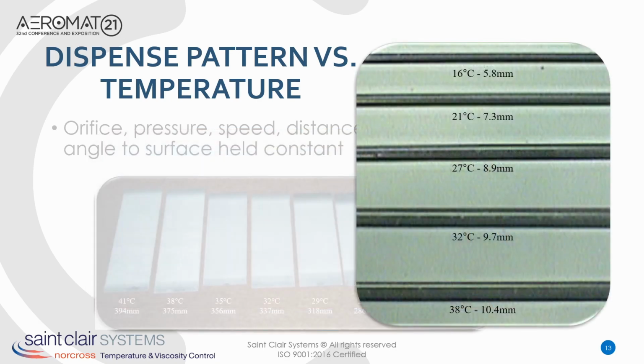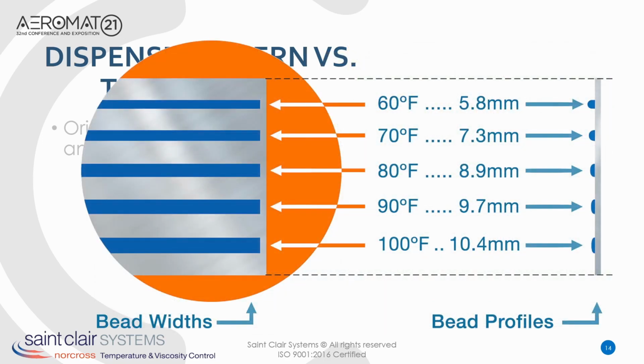In this typical hemflange application, the change in width of each bead as a function of temperature is obvious, with the width at 38 degrees C nearly double that at 16 degrees C. Perhaps not so obvious, though, is that because each bead is comprised of the same volume of sealer, the change in width is offset by a change in height. The wider beads are also flatter. This is often referred to as spread or slump and can significantly compromise the function of the bead. Without the proper profile, obtaining optimal adhesion to both surfaces is next to impossible. Moreover, if the material moves out of the designated area, it can create not only functional issues, but aesthetic ones as well.